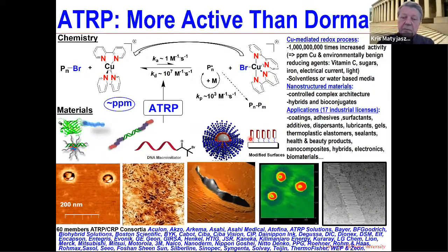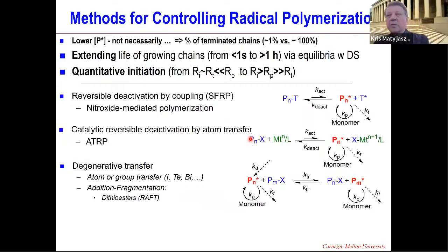So sometimes when people ask, what is a prerequisite? What is the most typical feature of a controlled radical polymerization, sometimes defined by IUPAC as reversible deactivation radical polymerization? Most people would say, you need to reduce the concentration of growing radicals much more than in a conventional radical process to prevent radical termination. And this is not true, because there are some very fast controlled radical polymerizations which can be completed within sometimes minutes, and they are still well controlled.